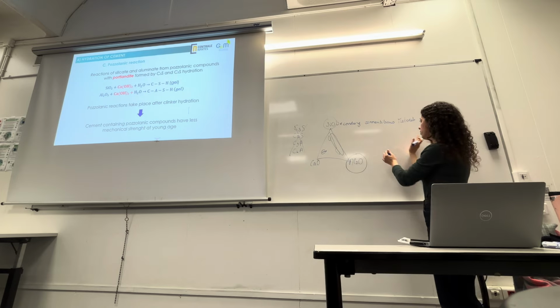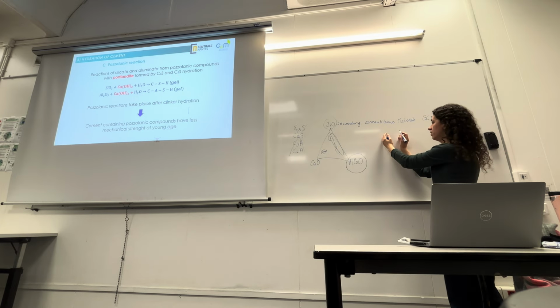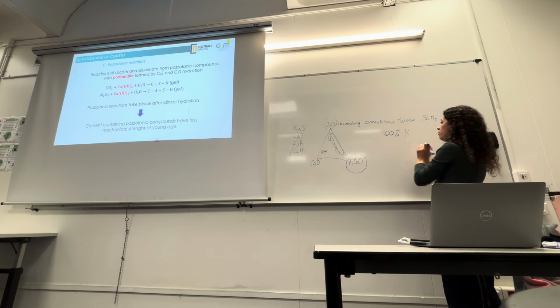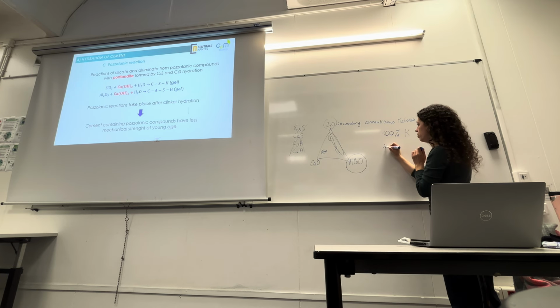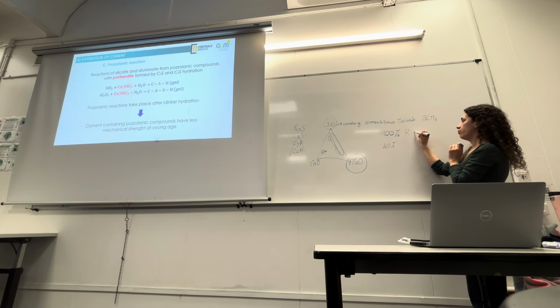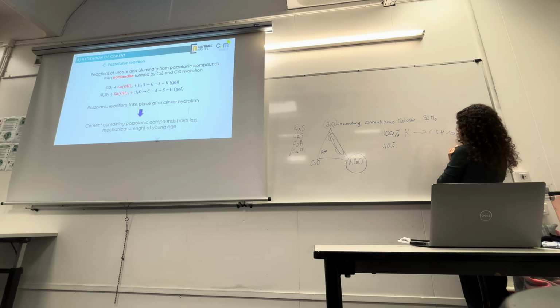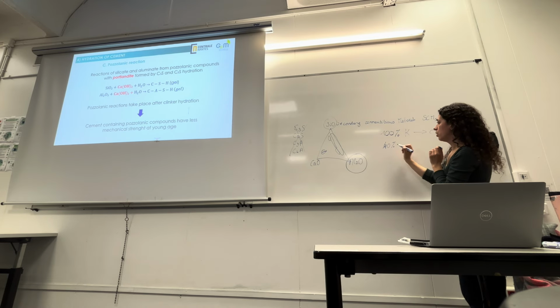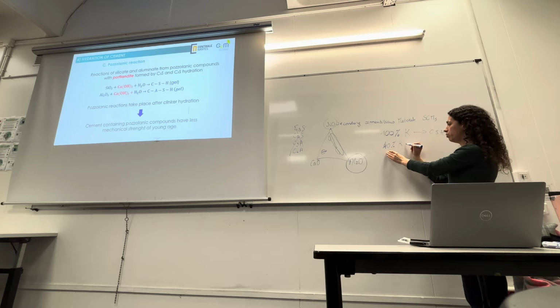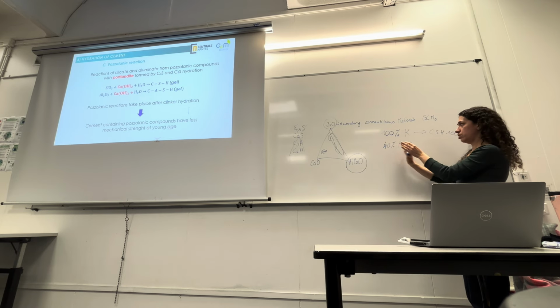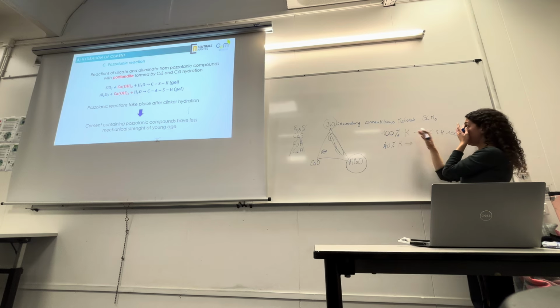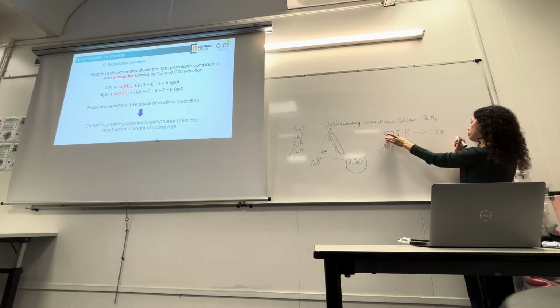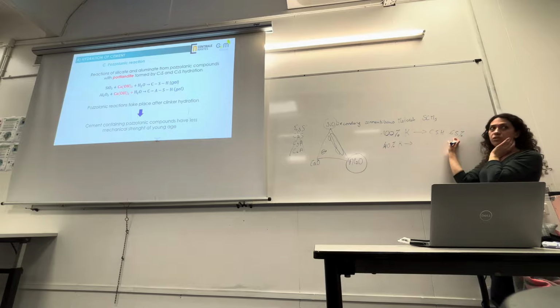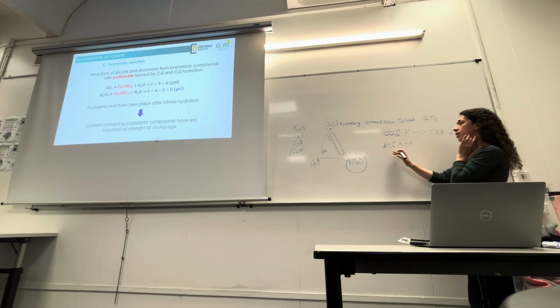Why? Because compared to a cement that is 100% clinker, cement that contains secondary cementitious material will contain only 40% clinker. So the 100% clinker cement will form CSH after hydration, while this cement will have the reaction of only 40% of clinker. As you remember, 100% clinker will give you 65% of CSH, the mechanical strength component.